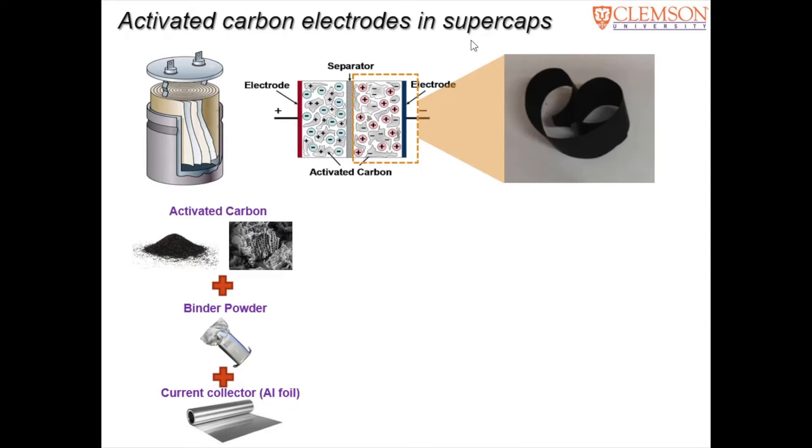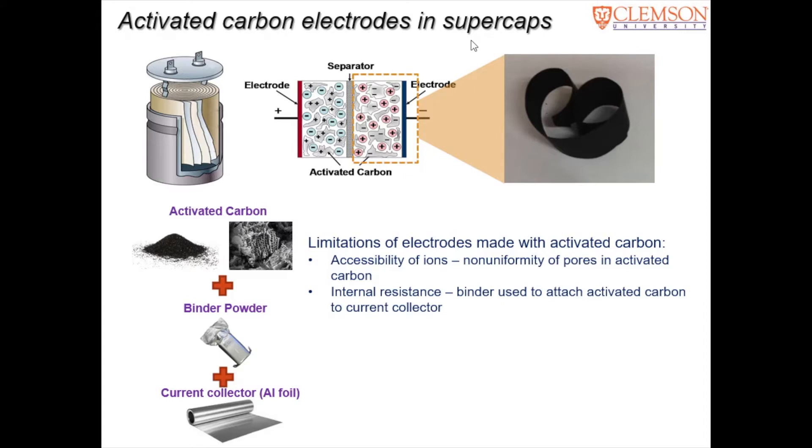However, with these kind of electrodes, there are still many challenges that we face. One is accessibility of ions—the electrolyte ions in the supercapacitors should have access to internal pores within the material so they can access the entire surface area for storing charge. Another issue is the resistance that comes mainly from the non-conducting nature of the binder that is used, and also carbon, although it conducts electricity, it's more of semi-metallic or semi-conducting nature and not a good conductor like metals.